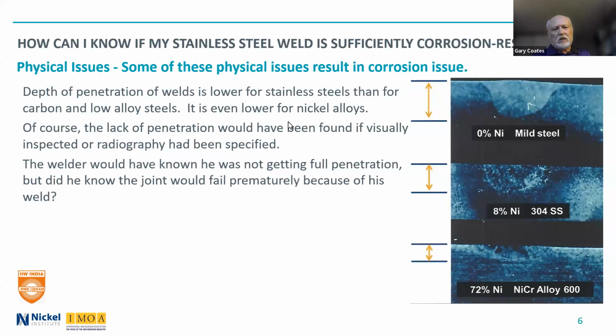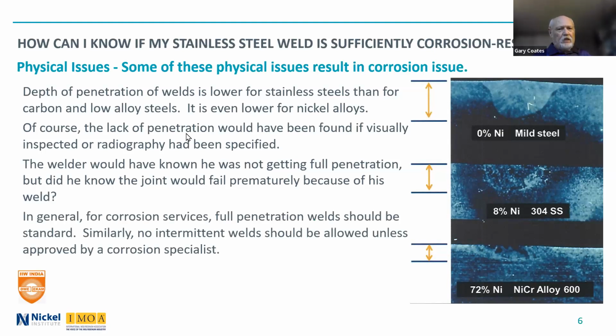Now, the welder would have known he wasn't getting full penetration, but he may not have known that the joint would fail prematurely because of it. And so a lot of it is communication between the welding engineer and the welder. Another way of getting at it is if there was a visual inspection of the inside of the pipe or radiography had been specified, that would have been clearly obvious. So in general, for corrosion services, we do want full penetration welds. And I would say, doesn't matter where it is, insist on full penetration welds.